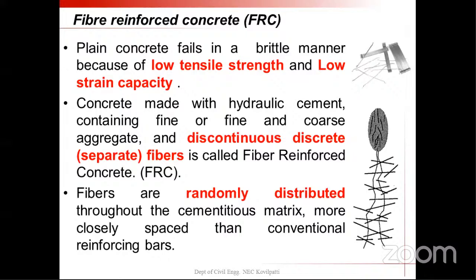So fiber reinforced concrete is not a recent technology. It was developed four to five decades back. So why are fibers added? Because concrete has very low tensile strength and low strain capacity. So that may cause a sudden failure or brittle failure of the structure. So in order to improve that property, in order to change the behavior of the concrete, these discontinuous fibers or discrete fibers are added inside the concrete.